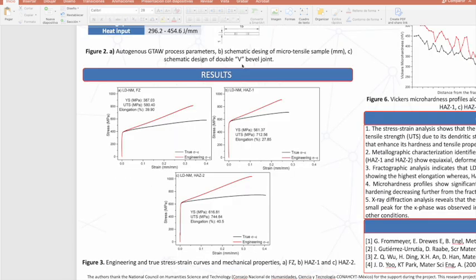Results. Figure 3. Engineering and true stress-strain curves and mechanical properties. Subsection A, fusion zone. Subsection B, HAZ 1, and subsection C, HAZ 2. Figure 3 illustrates the engineering and true stress and strain curves for the studied zones. Different behaviors were observed in each zone due to the varying heat input conditions. Generally, the results showed the fusion zone exhibits the lowest yield strength and ultimate tensile strength because of its dendritic structure, which also corresponds to the lower hardness observed. Added to this, the maximum elongation was reached in HAZ 2.